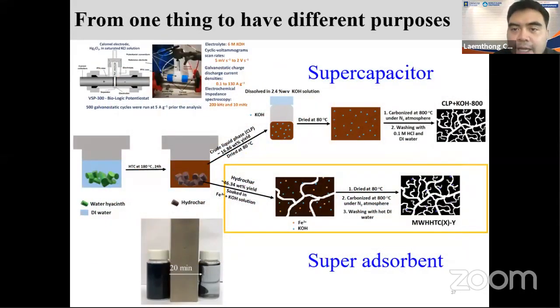Okay. So in our technique, using the same hydrothermal carbonization, instead of sugarcane bagasse we put water hyacinth into the system, and we do the same thing. We do a kind of activation using the hydrothermal process. The hydrothermal gives you two things, a solid product and a liquid product. For the solid product, we do further activation with iron and potassium hydroxide. You can notice that we use potassium hydroxide again.